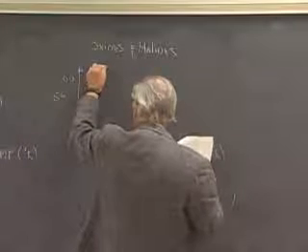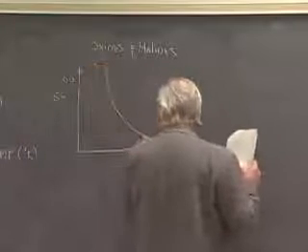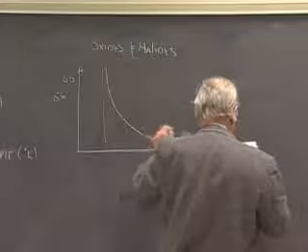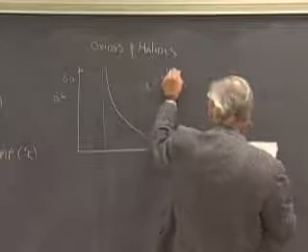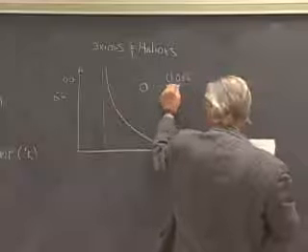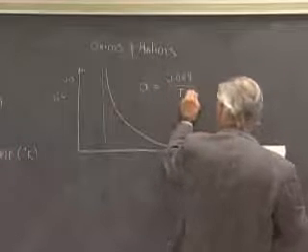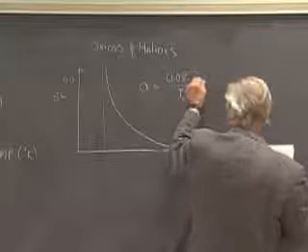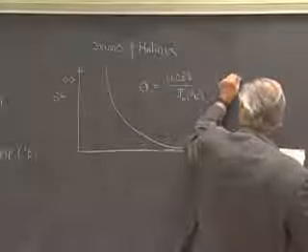And again, a variation with 1 over T, but offset from the origin. And the curve here is that A equals 0.038 over T, the melting point, T sub m in Kelvin, minus 7.0 times 10 to the minus 6.